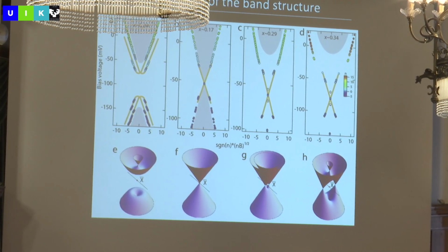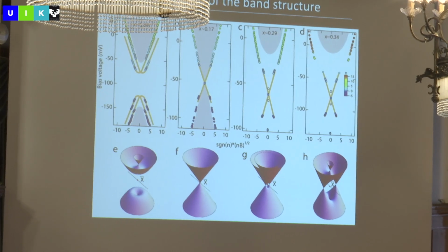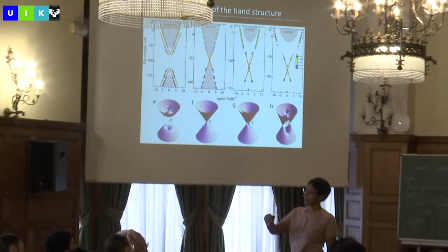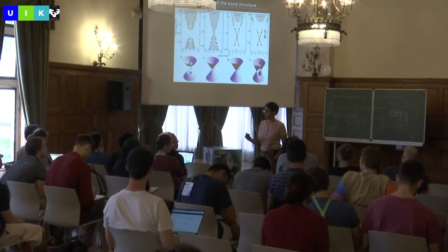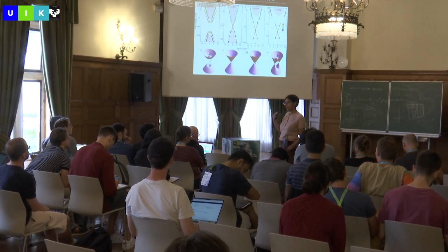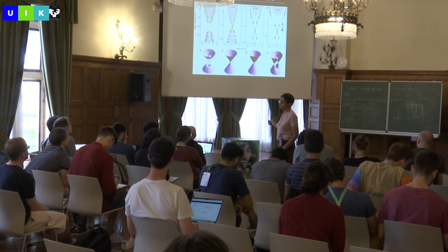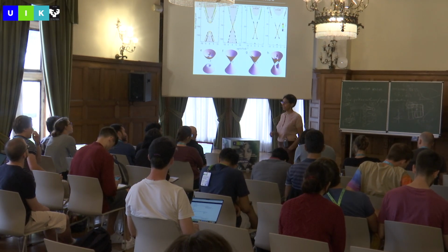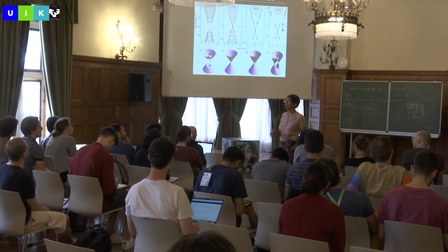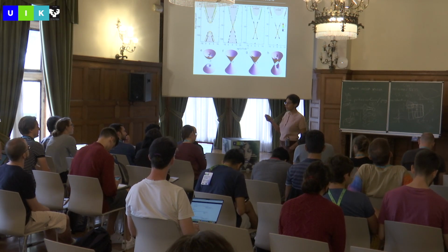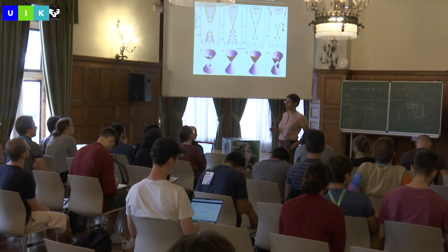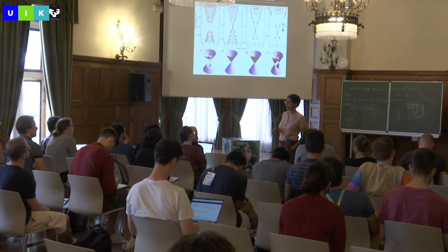Is there also Rashba in the bulk? Let me answer it this way. The system has strong spin-orbit coupling. Okay? And so the strong spin-orbit coupling leads to this kind of a surface state. This happens even in gold, for example. So in gold, there's a surface state, there's strong spin-orbit coupling, and you see that the surface states have split due to that strong spin-orbit coupling. Okay?